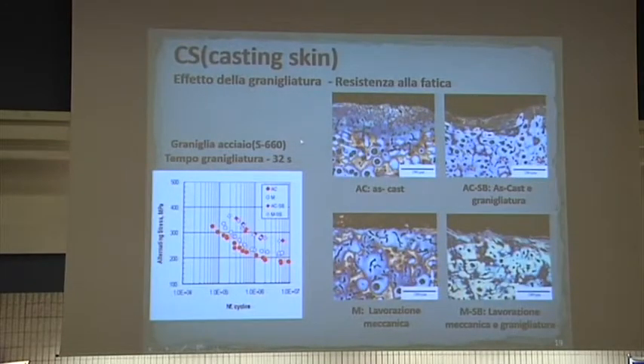And here are some examples of the effect of shot blasting. You can see how the surface is affected by shot blasting. You see a lot of deformation, plastic deformation. And here is a comparison: as cast and shot blasted, machined, and machined and shot blasted. And you see, once you shot blast and machine, there is not much difference. And the effect of the sand, sodium silicate and furan sand, you are going to find different effects depending on the sand.